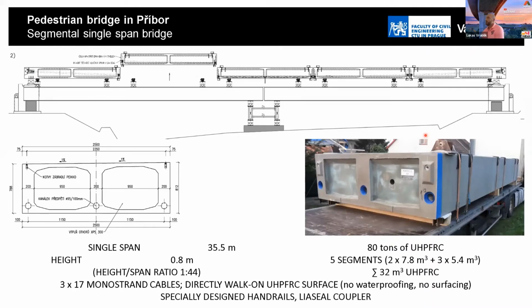As you can see on this information, the total length of the single span structure, or the length of the span, is 35 meters. The height of the cross section is only 0.8 meter. If we want to produce something like a height to span ratio, it is 1:44. It is completely out of normal idea about this type of structures, because normally we use this ratio approximately 1:20.